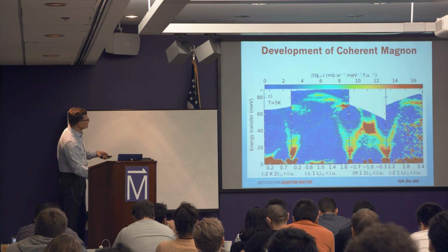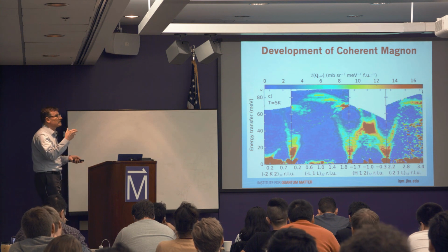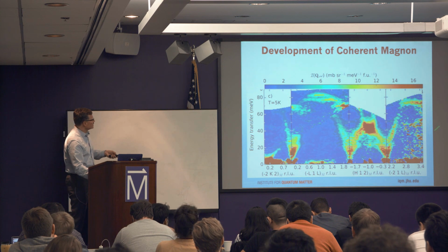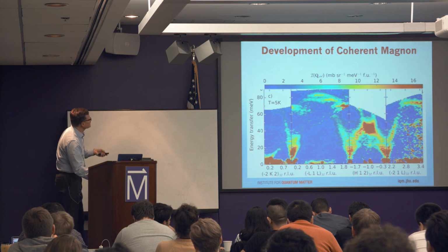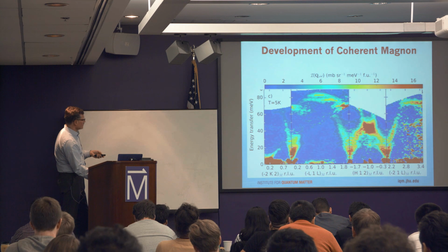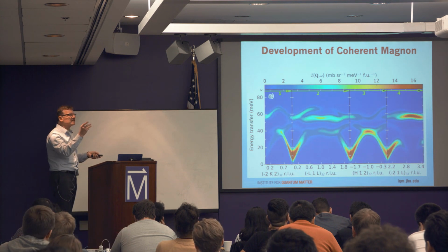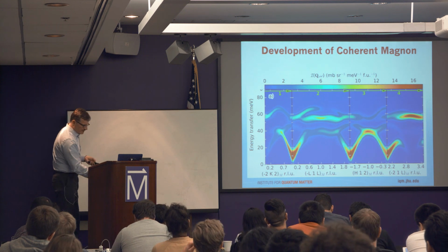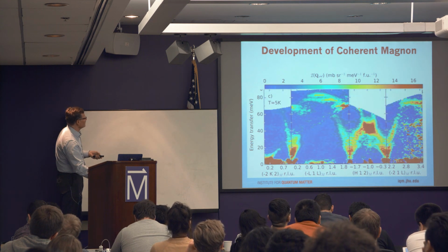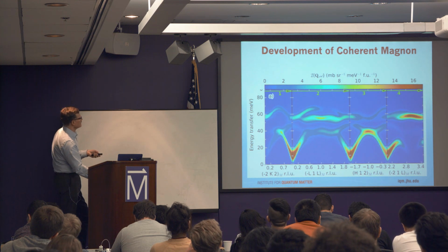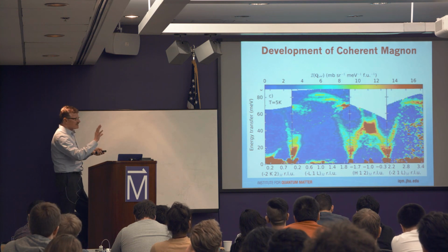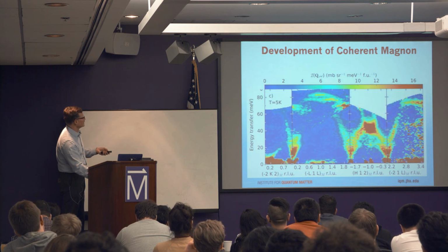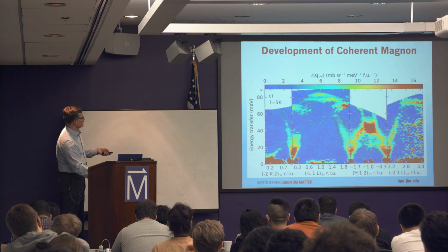These actually will be things that we can analyze to obtain experimental values for the exchange constants. And so what we did in terms of comparing to theory is that these are measurements of spin waves in the ordered magnetic state. Then we take the DFT calculated exchange constants, and we can calculate this kind of spectrum. It's not quite the same, but the bandwidth is pretty good, and many of the features are there. If we allow ourselves to adjust the exchange constants to have the optimal agreement with the data, then we end up with this kind of agreement, which is really pretty good.